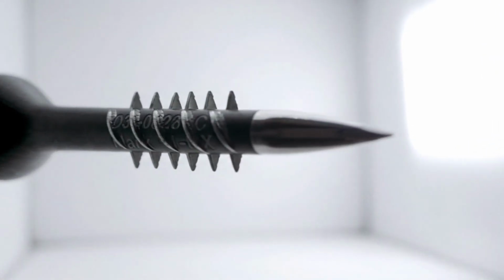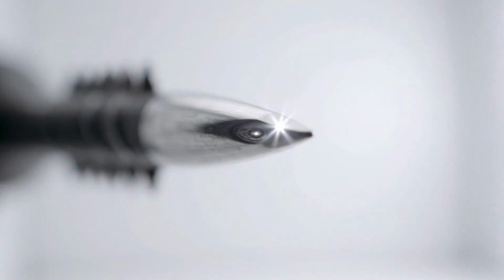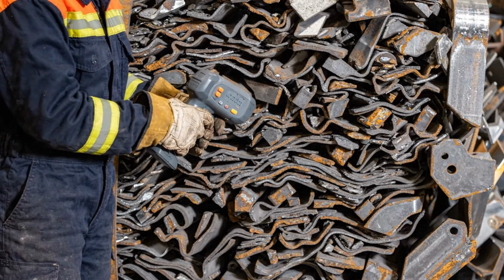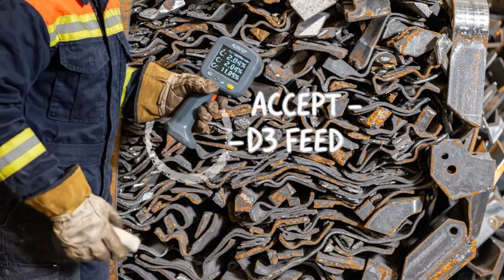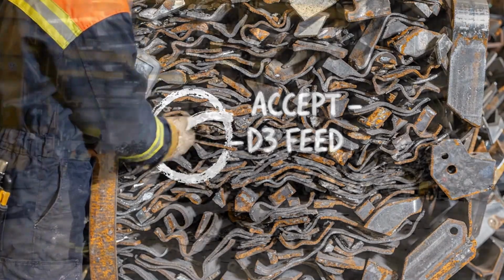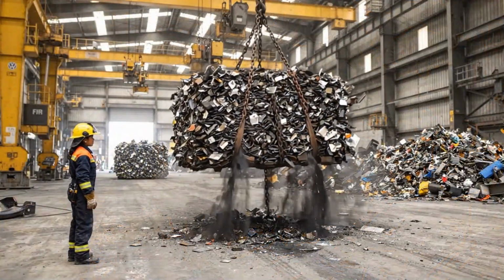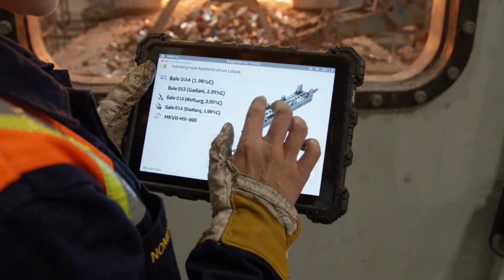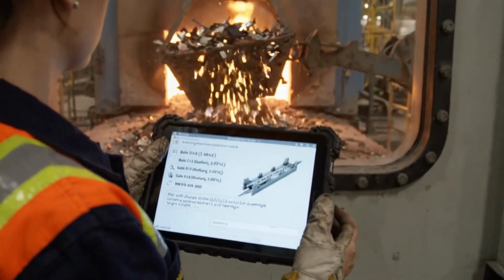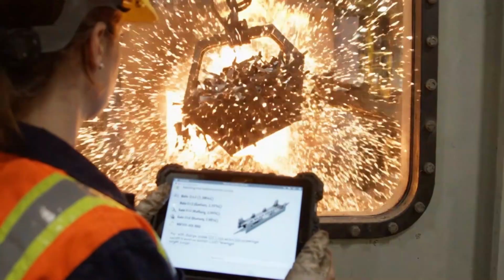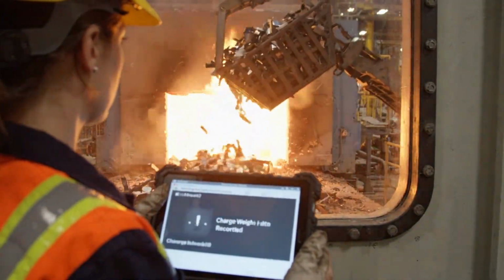From the broken hulls of ships on a Pakistani shore to the mirror tip of a needle that will pierce ballistic armor, the Wolfsburg offcuts arrive pre-alloyed with chromium and molybdenum from their original tool steel specification, a metallurgical inheritance. The charge blend algorithm calculates the optimal scrap mix for every furnace heat, ensuring that the final billet chemistry never deviates from the D3 specification.